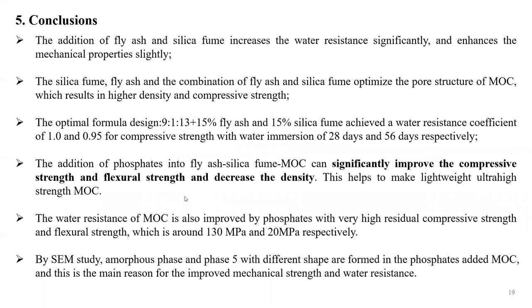So before I finish, I would like to conclude. The addition of fly ash and silica fume increased the water resistance significantly and enhanced the mechanical properties slightly. The silica fume, fly ash, and the combination of silica fume and the fly ash optimize the pore structure of MOC, which result in higher density and compressive strength.